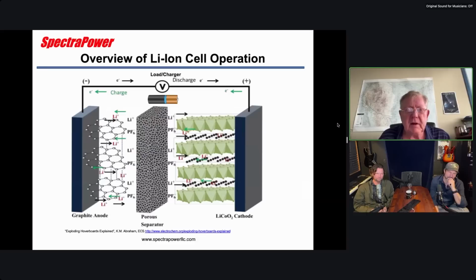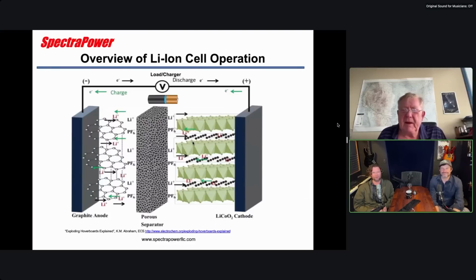It's typically either mostly polyethylene, sometimes polypropylene, which are very inert plastics. Very thin sheets, down to about 5 microns. That's all that's keeping these electrodes from shorting. Wow. And polyethylene also has a negative feature in that it shrinks and melts at a fairly low temperature. So one of the problems is if these cells get too hot, then this polyethylene can be close to where it might start shrinking. And when that happens, you're losing separation and can cause a short.